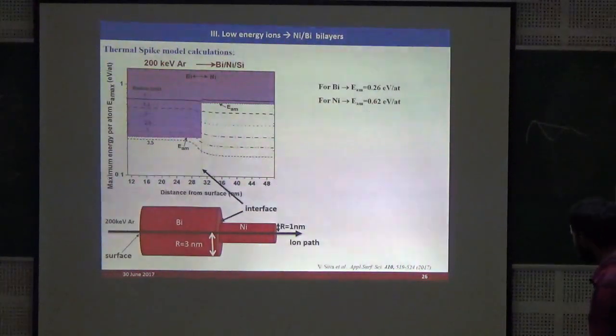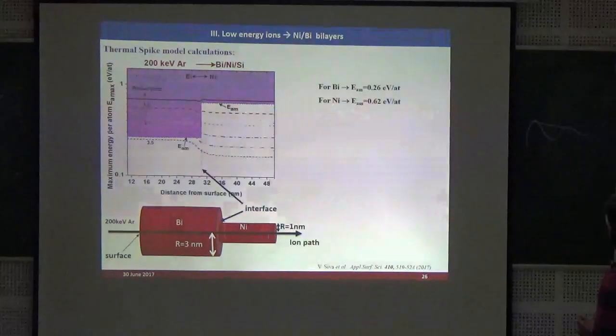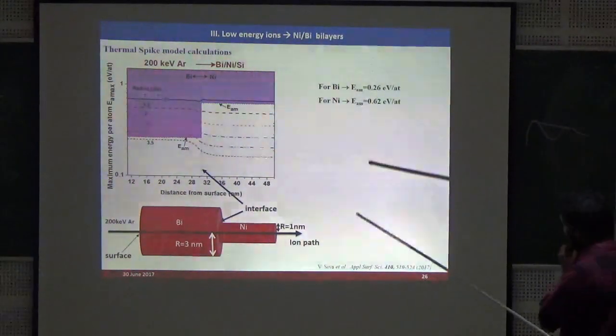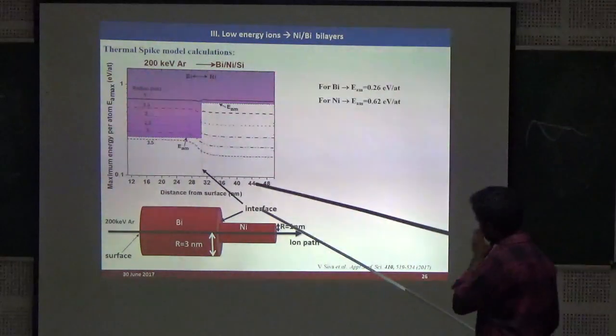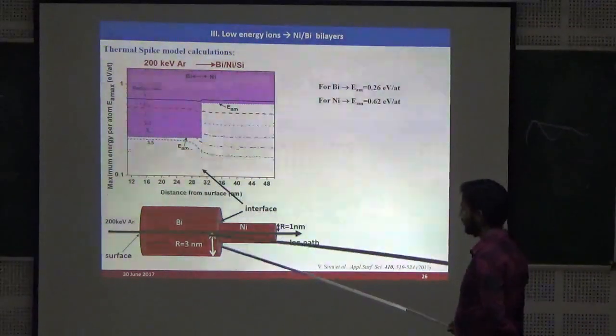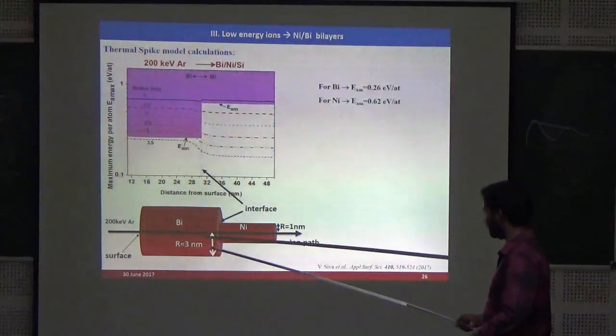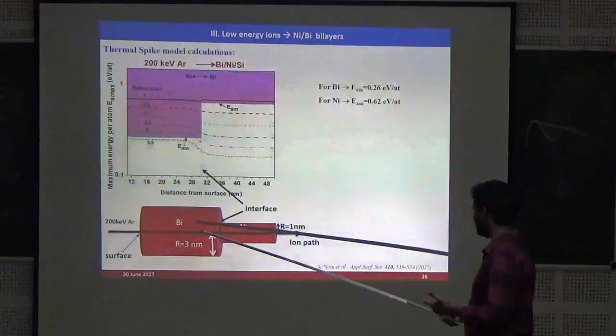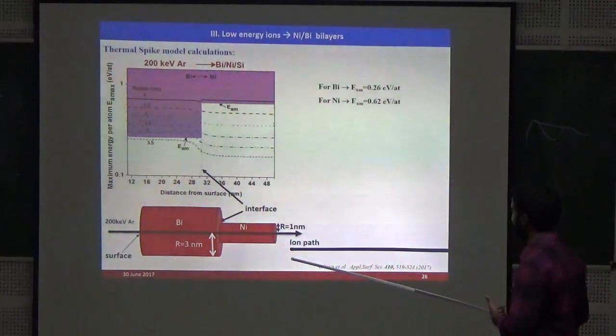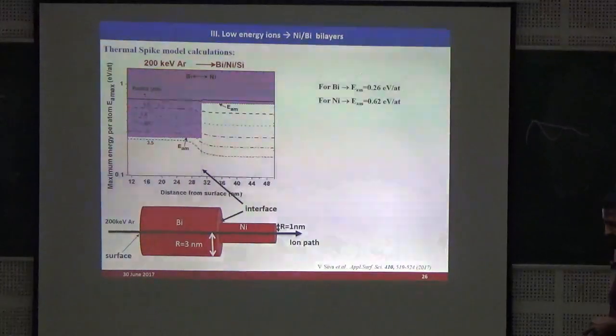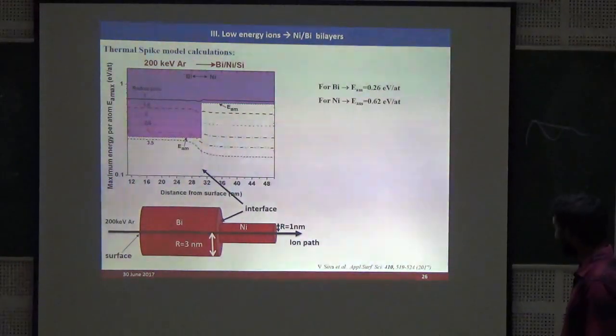To understand what was the reason for this mixing, we have performed thermal spike model calculations where we have seen like 3 nanometers of latent track in case of bismuth and 1 nanometer of latent track in case of nickel. So here in this case the ion track radii is less. That is the reason why we have seen less mixing in this case compared to the medium energy.